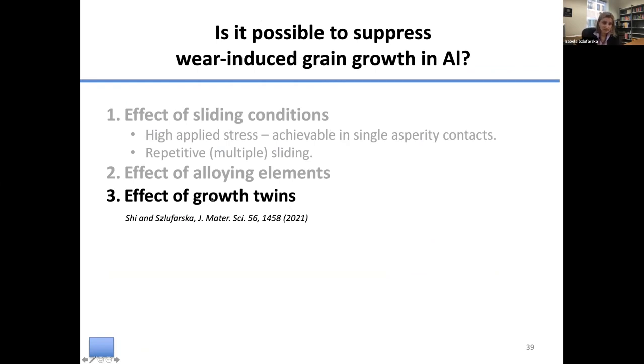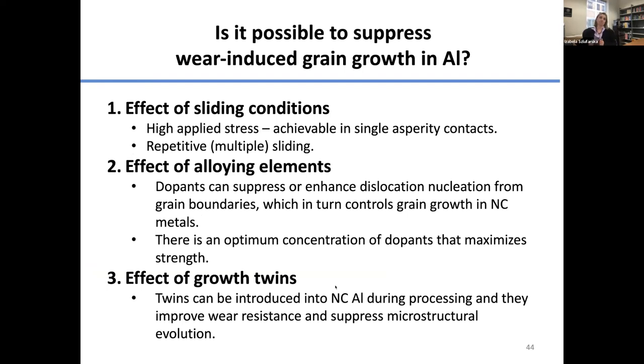I don't have time to talk about the grain boundary twins. I encourage you to read our recent paper on this, but let me just jump to the conclusions. For the second part of my talk, on plastic deformation, I've shown that we can have grain refinement in aluminum, which is exciting, since it's a high stacking fault energy material, and that can be accomplished at reasonable stresses. There's a transition from grain growth to grain refinement as a function of increased stress. I have also shown you that dopants can be used to control the microstructural evolution. A lot of the way they do that is by controlling dislocation activity and emission from grain boundaries. Whether the dopants will do that or not depends on the specific dopant and how much free volume it induces into the grain boundary. And for twins, I'll just stop right here. You can have a look at the paper, but at this point I'm happy to thank you for your attention and answer questions.